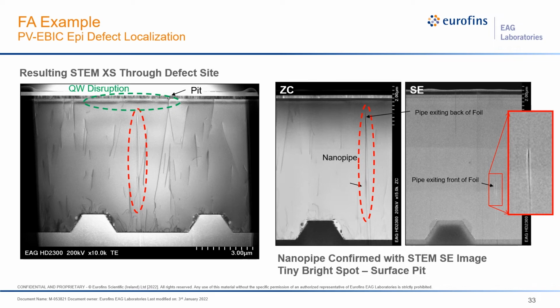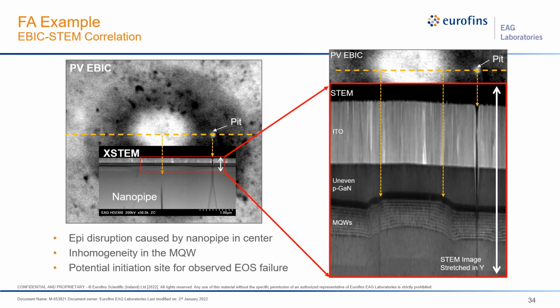And in our dedicated STEMs here in North Carolina, we have secondary electron detectors where we can actually look at the surfaces of the foil. And so you can actually see this bright up, which is a signature of a void or a hole. And so in this case, we've got a nanopipe that spans a large portion of this cross section. So you've got to remember this cross section itself is about 150 nanometers thick. So you can see it leaving the foil down here, and it extends up through the foil and then leaves here again. But this feature itself is actually centered on this quantum well disruption.